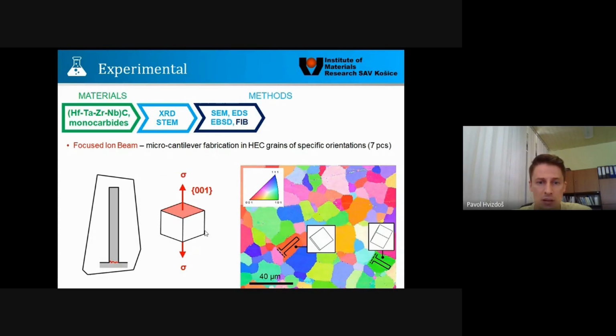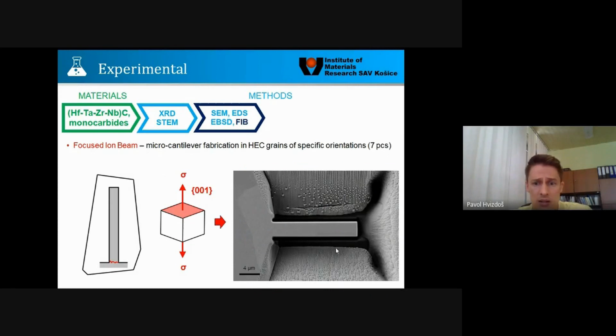using focused ion beam technique. Regardless of the top orientation, the fixing was always parallel with the 001 direction. So that kind of cantilevers were intentionally fabricated such that they were parallel to the surface of 001. This 001 has the lowest fracture energy based on some DFT calculations. So that was the reason why we selected this specific orientation. As you can see on the right side, here is how it looks, the as-fabricated cantilever, which was used for testing.